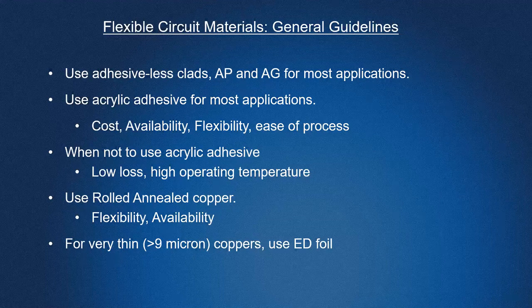Chris, I'm sorry, what's a good maximum temperature for these acrylic adhesives, do you think? So its rated operating temperature is 105 Celsius. I've known people to use it up to 125 in continuous operating conditions, not a problem. Its decomp is 315 Celsius, so the decomp is pretty high. What happens with the acrylic adhesive is it will soften at the higher temperatures, but as soon as it's cooled, it goes down to its normal condition.